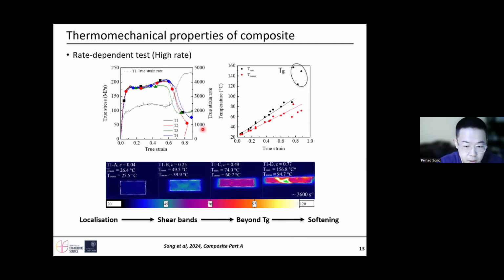Again, I used the same method to characterize this material at the high strain rate. As we can see, the stress drops at 0.6 true strain. From the temperature rise mapping, so from the thermal image, we can see the localization at the beginning, and then shear band formation. At the end of this test, we see the maximum temperature is above 150 Celsius, which is beyond the glass transition temperature of the polycarbonate. So that caused the softening.